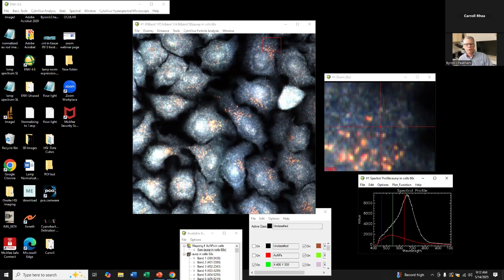One of the things you can see if we focus on the cell here where my cursor is, I'm outlining the nuclear membrane of this cell and the nucleus here, and outside of that would be the cytoplasmic, the non-nuclear area of the cell. And if we look across these cells, we can see that nanoparticles seem to be mostly aggregating, probably in cell vacuoles outside of the nucleus, not crossing the nuclear membrane, which makes sense. These nanoparticles, before they were taken up by the cell, were around 40 nanometers in size. That's too big alone to generally cross the nuclear membrane. And so we can observe that qualitatively as we see here.